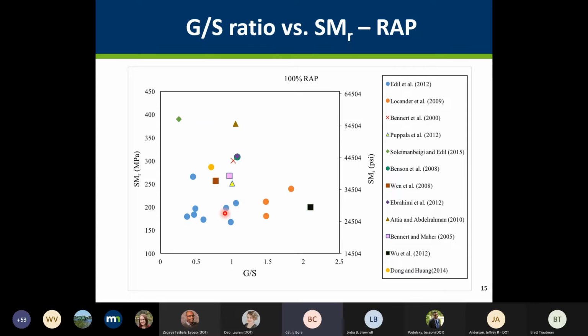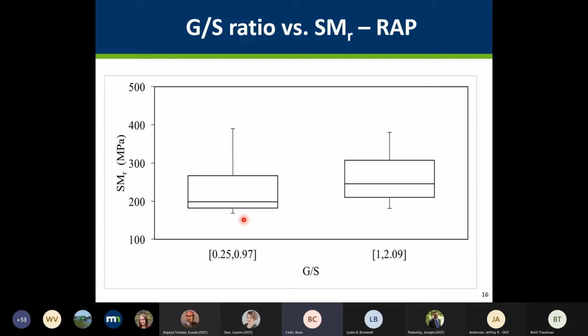We have a lot of figures in the final report that is uploaded on the NRRA website for this project. We correlated these summary resilient modulus values with a lot of index characteristics, and did the same with the strength parameters, permanent deformation, and hydraulic conductivity. But here I will mainly focus on the behavior of some index characteristics relative to the resilient modulus values. In this figure, these are the papers from which we collected the data. On the y-axis, we have their summary resilient modulus values with their corresponding gravel to sand ratio. As you can see, there is no consistent trend between the gravel to sand ratio of these materials and their summary resilient modulus values. So we try to put them in different groups.